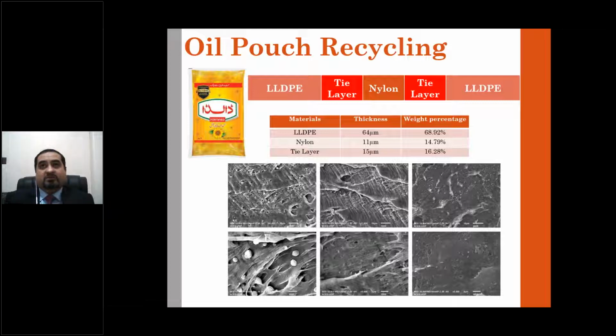When we try to process these materials through thermoplastic processing using extrusion, we found out through scanning electron microscopy results that there was clear phase separation between the nylon and the LLDPE. Then we tried to enhance this through various compatibilization techniques, and this research is still being conducted, so that is why I have not included the result. But just to show you that these are the problems you will end up with if you try to recycle these multi-layered structures directly. You then have to make sure that you incorporate some other modification techniques in terms of compatibilizers, in terms of chemical modification, to get the desired results.